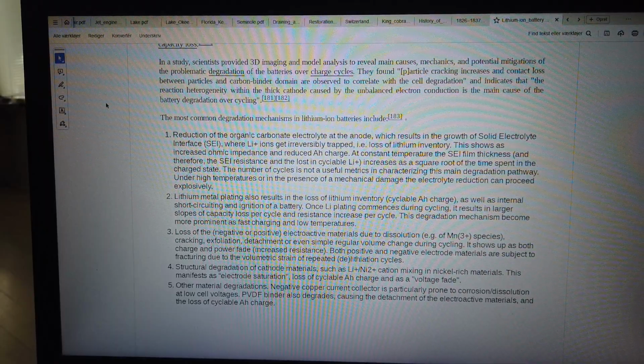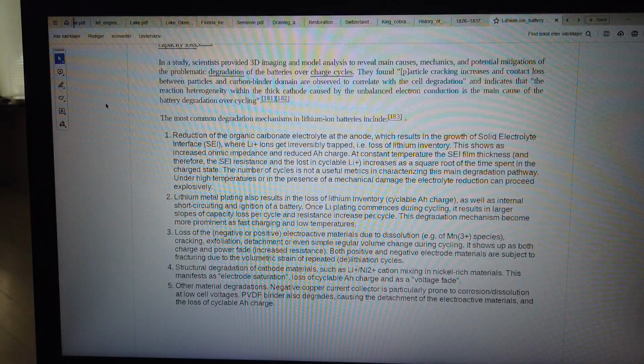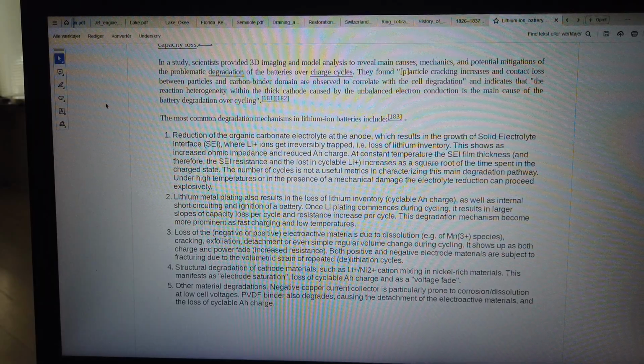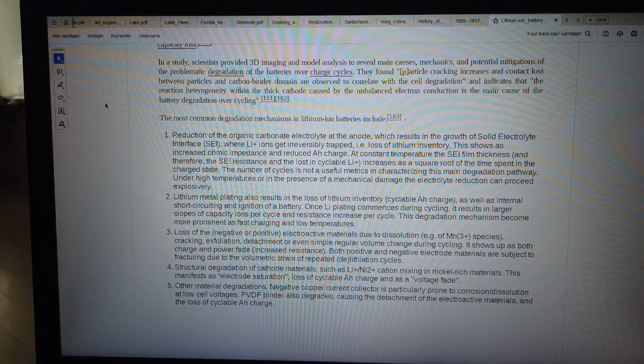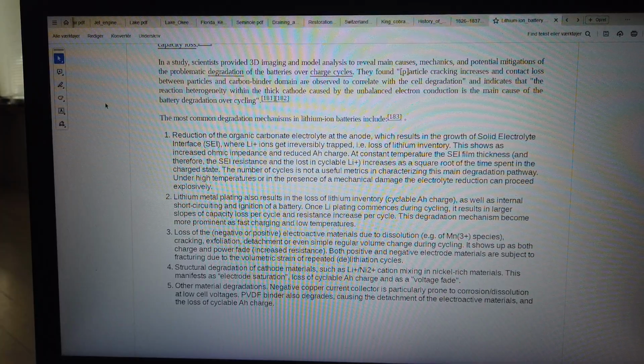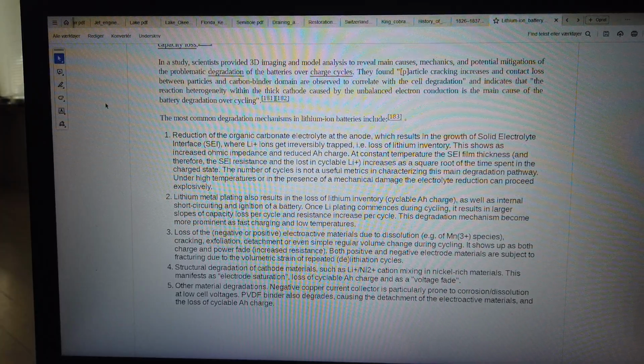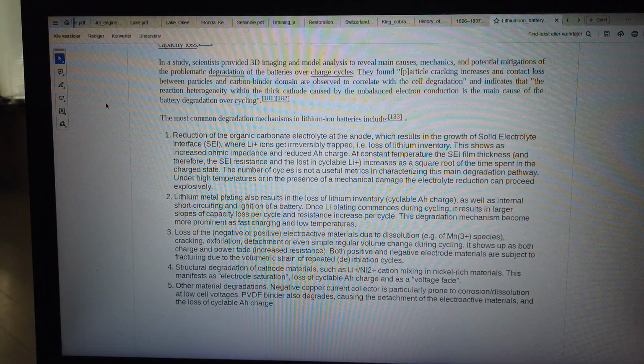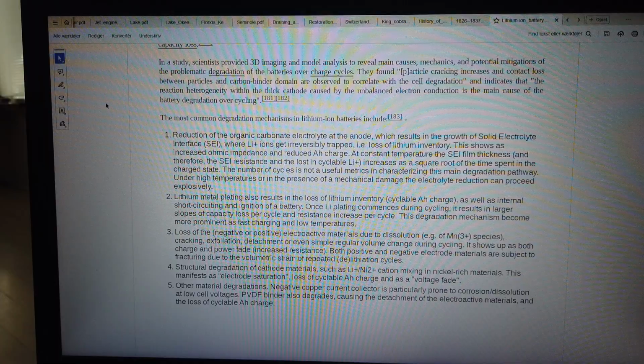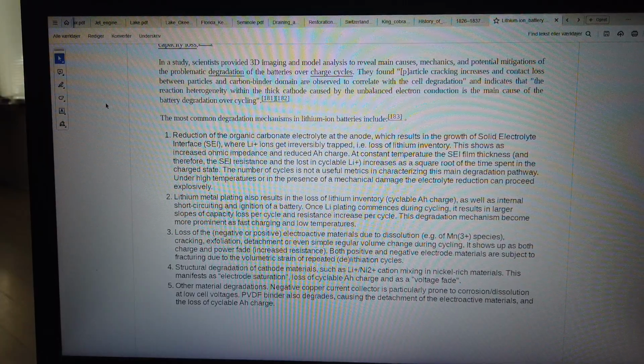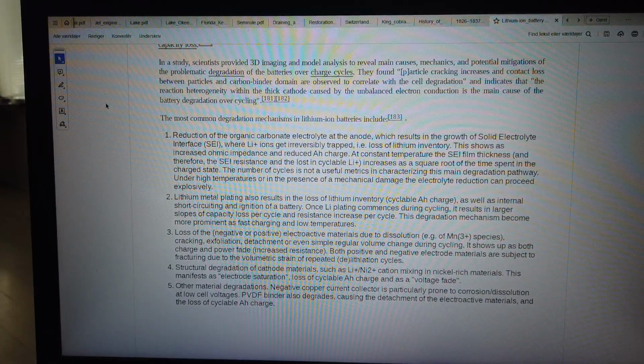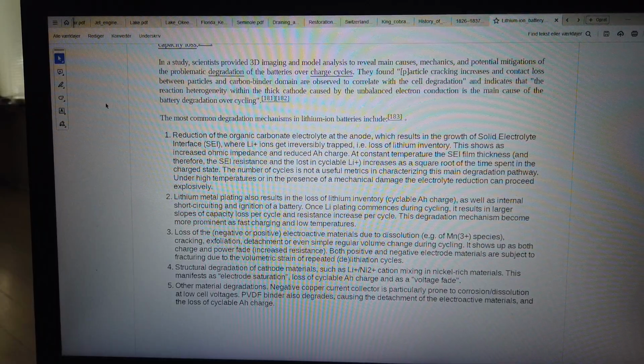Under high temperatures or in the presence of mechanical damage the electrolyte reduction can proceed explosively. Lithium metal plating also results in the loss of lithium inventory, cyclable charge, as well as internal short-circuiting and ignition of a battery. Once Li plating commences during cycling, it results in larger slopes of capacity loss per cycle and resistance increase per cycle. This degradation mechanism becomes more prominent with fast charging and low temperatures.